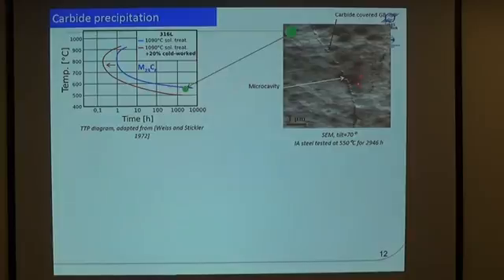Now we did the same for the IA steel here. All this is the IA steel that shows most of the damage. For different temperatures at which this was held. And actually we see that the most detrimental temperature is the one between 550 and 600. It's 575. So actually there's a maximum here.